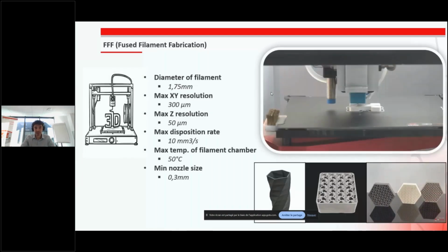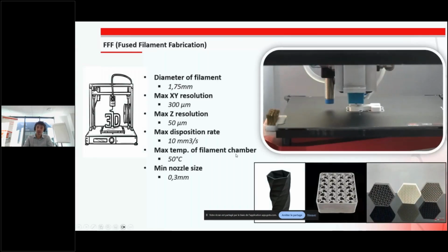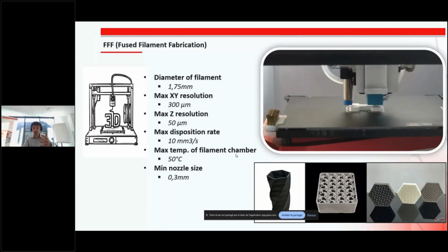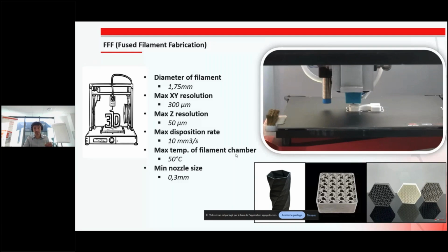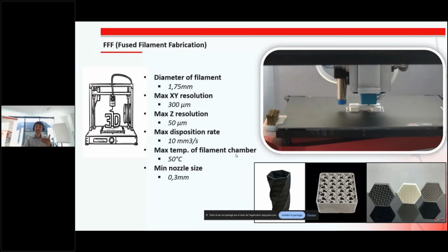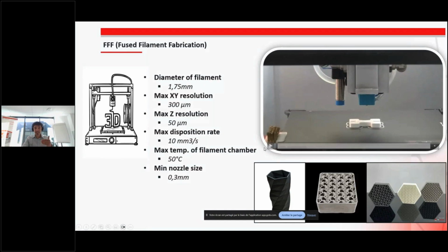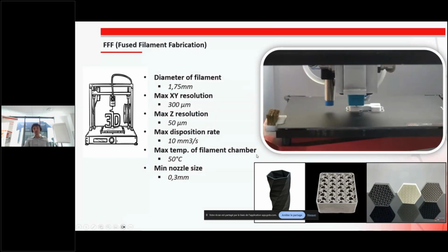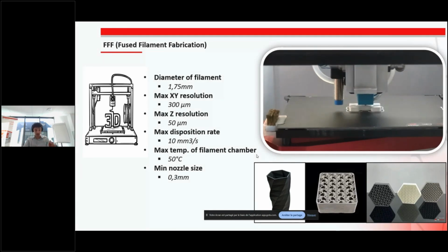So here, for instance, about FFF. FFF is a well-known process. Probably most of you already use the FFF process for plastic printing. For instance, a filament goes through a nozzle. It is exactly the same with ceramic filaments. If you don't know, keep in mind that it is possible to print ceramic parts with the FFF process. For instance, on the video, you can see a zirconia part during the printing process, and on the picture, you can see zirconia, alumina, and the black and gray parts are SiC, silicon carbide.